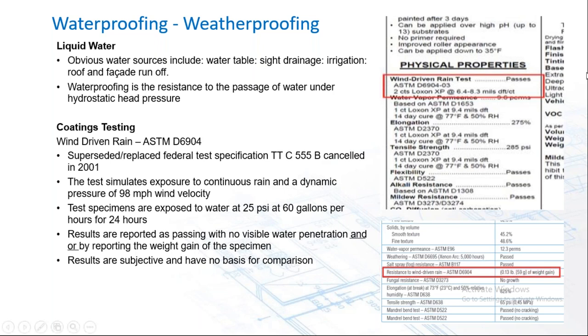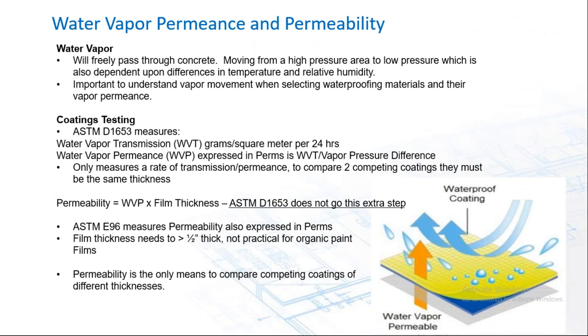Water vapor permeance and permeability. And this is a real mind bender. There are four different tests, wet and dry cup, as well as the ASTM D1653 and E96. But essentially, the coatings industry has really fallen in behind the ASTM D1653. However, what it does in the first process of its measurement is determine water vapor transmission, WVT, which is grams per square meter per 24-hour cycle. Then a calculation gives you water vapor permeance. And this only measures a rate of transmission or permeance. So to compare two coatings, they really have to be of the same thickness. And the calculations within the test of ASTM D1653 doesn't actually take that step to